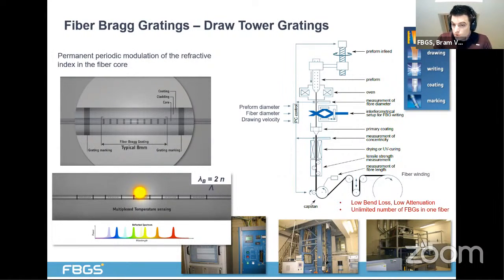And also important, the primary fiber coating is only applied after the grating is inscribed. So when the fiber is coming off the tower, the gratings are inside, the coating is on, and we basically still have the pristine strength of the optical fiber maintained, so that it is not affected by the inscription of the gratings.